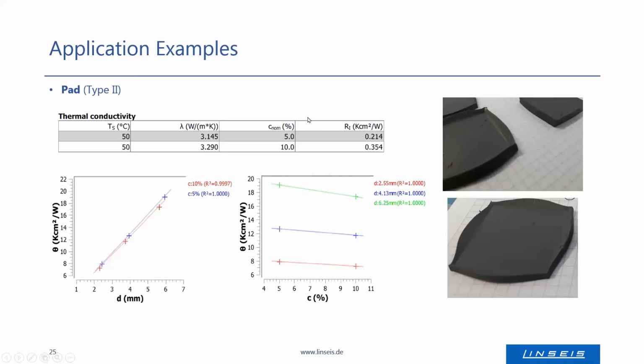So the end result shows that with higher compression, thermal conductivity also gets higher. To illustrate that, there is a diagram showing the thermal impedance in dependence on the compression, and also the dependence on the sample thickness.